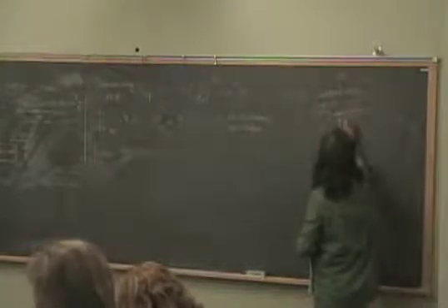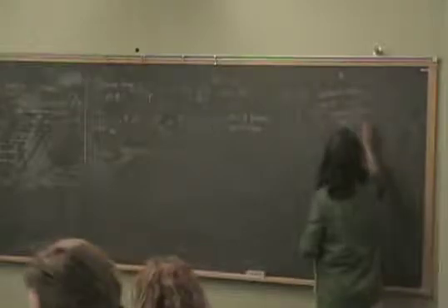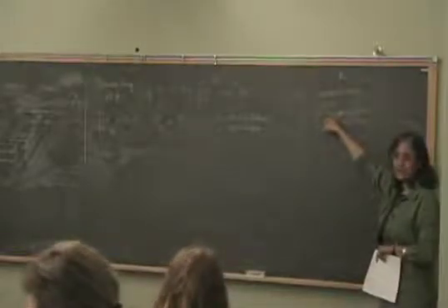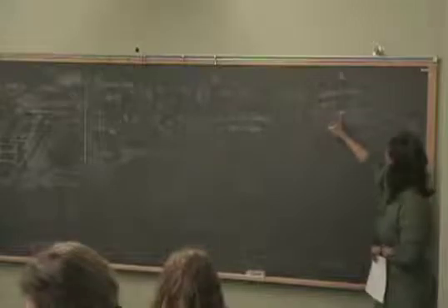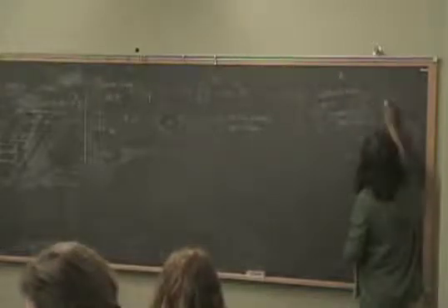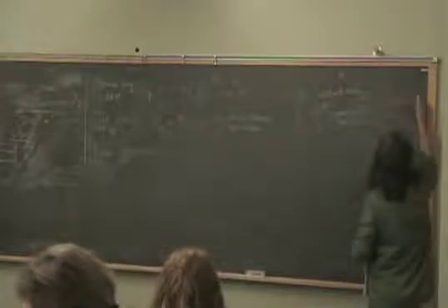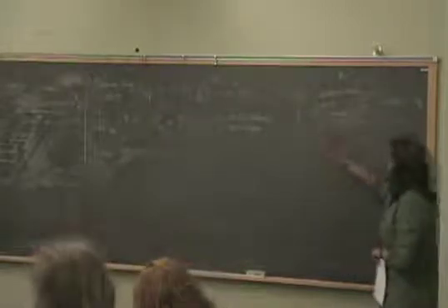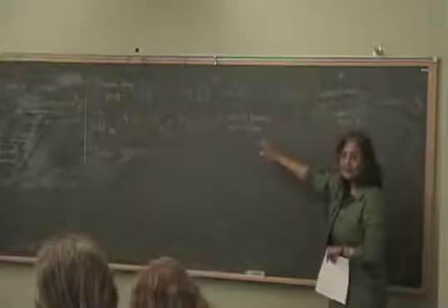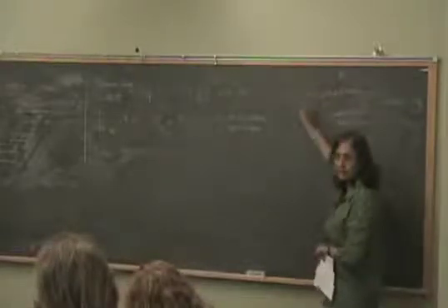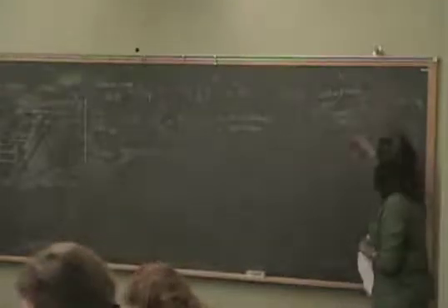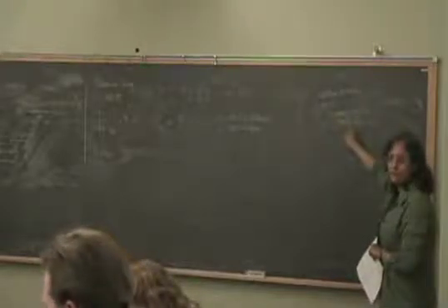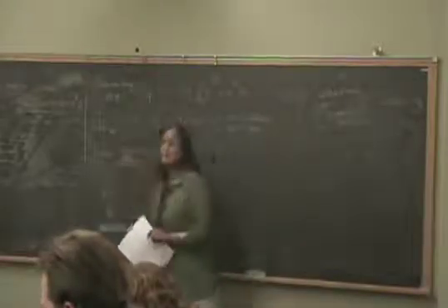But then at about 9 eV here, this is omega, so let's say h bar omega here, we have the plasma frequency. And that is defined by that frequency at which epsilon goes to 0. Above that, epsilon of omega becomes 1 minus omega p squared over omega squared. So the part that this model treats does not describe any of the interband stuff. It is just a free electron gas. So it's basically describing this part of the physics, and it says in bulk it would have absorbed at about 9 eV. Now the first thing that we have to bring in is what happens if it's a sphere.